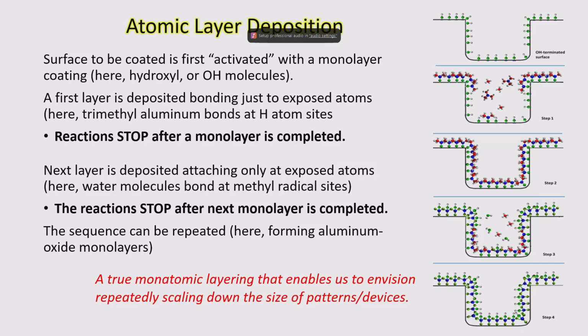So you'll see that a surface is first prepared with an activating process. In this case, there are hydroxyl radicals with the oxygens attached to the surface, exposing the hydrogen atoms. Then you can introduce a compound, in this case, trimethyl aluminum. It's an aluminum atom with 3 methyl radicals attached. And they will attach, but only at those places where there's an exposed hydrogen at the surface. And therefore, it means that only one molecular layer will be deposited. Once a given site is taken, no more molecules will attach there.